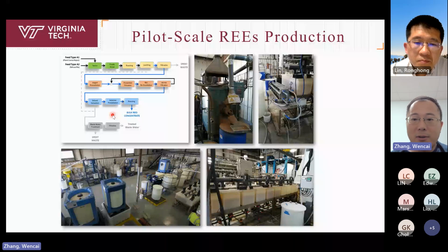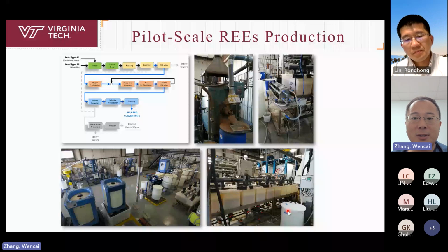We also have a very small line for the oxalic precipitating rares, which is not shown in this picture. The line is very small, and this is understandable because the rares content in coal refuse is so low. There's only around 300 milligram per kilogram of rares in our feedstock.